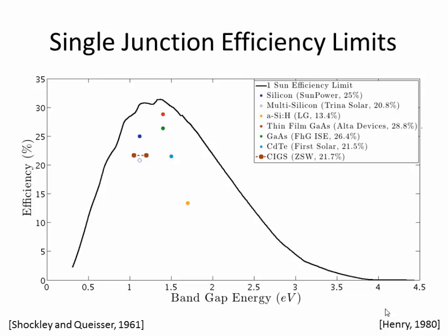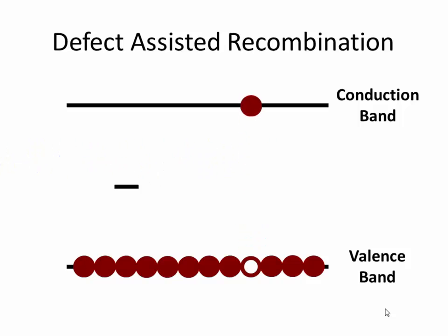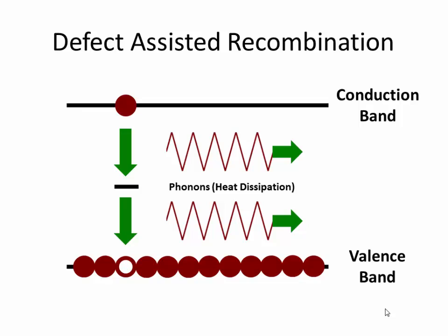One of the conditions to actually reach the limiting efficiency is that all of the recombination in your device is purely radiative. So any non-radiative recombination, like when we absorb a photon and it recombines across the band gap, releasing heat, releasing phonons instead of photons, anytime that happens, we lose carriers, and it reduces the efficiency below the limiting efficiency.